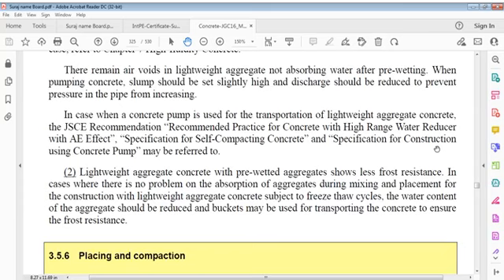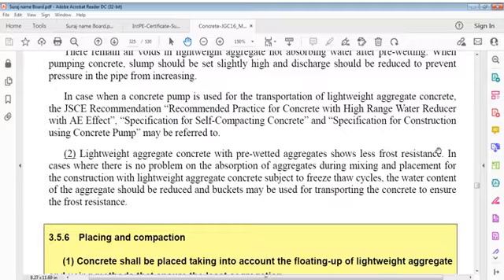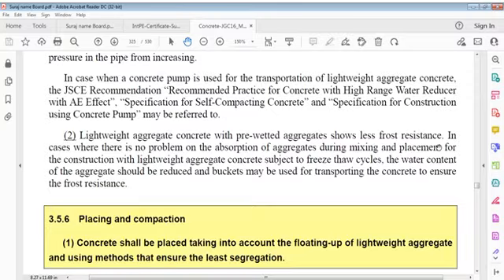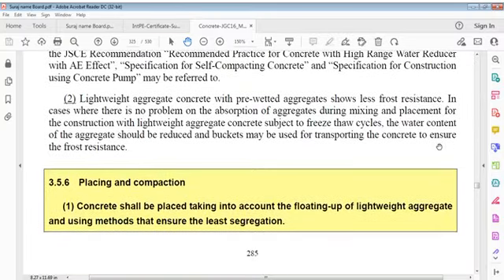When pumping concrete, slump should be set slightly high and discharge should be reduced to prevent pressure in pipe from increasing. In case a concrete pump is used for transportation of lightweight aggregate concrete, recommendations we have to see about concrete with high range water reducer with air entraining effect. Then specifications for self-compacting concrete and specifications for concrete using concrete pump.